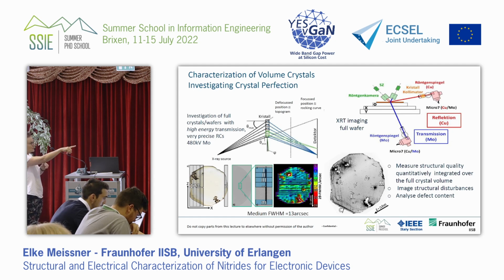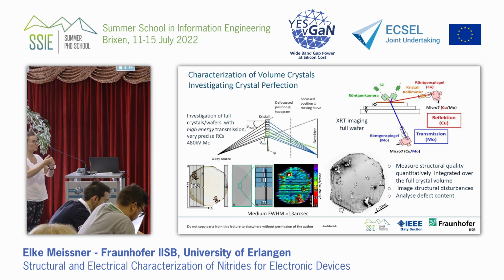Which you can see here, for example. Do you see this colorful map? This is a map in the defocus mode, where we see the rocking curves. So we see this is a heat map of the full width half max in arc seconds over the whole crystal. And it's a sum through the whole crystal. So the thickness of the whole crystal is summed up here, the total volume. And we see that there are places where we have less good quality.